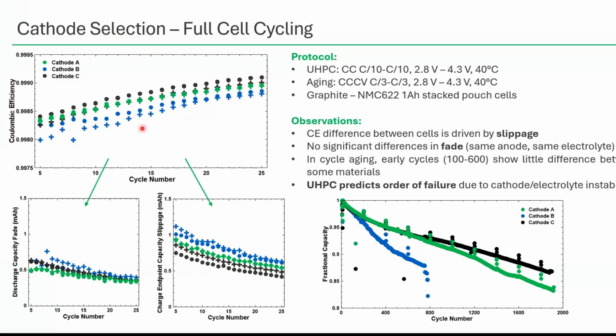What's interesting here is when we break this down into the two constituents or main contributors to Coulombic efficiency, we see the discharge capacity fade and the charge endpoint capacity slippage. These are shown on the same axis to demonstrate that the main driver of the differences in Coulombic efficiency is not how quickly the cells are losing capacity. It's actually these other more invisible mechanisms like electrolyte oxidation at the cathode, like transition metal dissolution from the cathode. These electron donating mechanisms are decreasing our Coulombic efficiency, not what is making the cell fade faster.